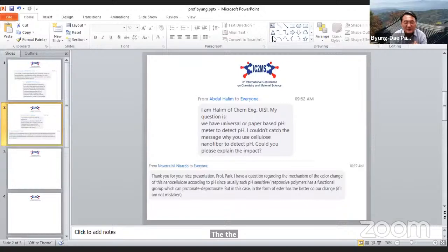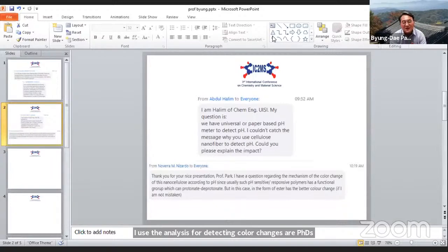Yeah, that's a very good question. As I mentioned, why I use the nanocellulose for detecting color changes or pHs, because you can use the pH indicators. You can put the pH indicator in the water, and you can see different pHs, and then you can see the change of colors. But what I'm thinking about is I try to make a kind of indicator film, or a film indicator. In that case, you can mix pH indicator with something or polymer. In that case, you have to think about how the pH indicator dye may be released from the matrix. This is not good when you are using the film or indicators.